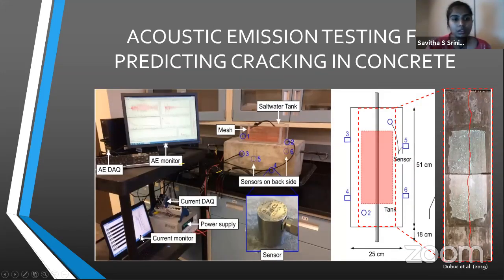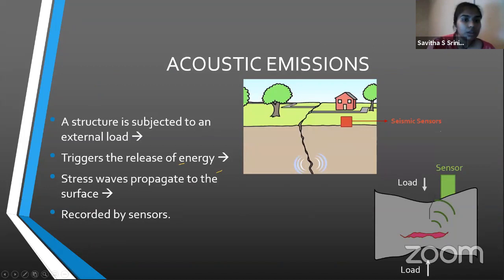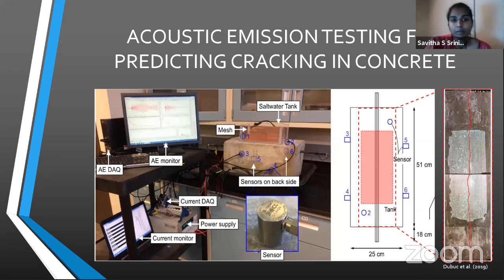So acoustic emission is more of a passive test because once you have a flaw, it will send out a pulse which goes to the sensor. So what we have here is an example of acoustic emission testing for predicting cracking in concrete. So we have a concrete block which is subjected to accelerated corrosion again, and